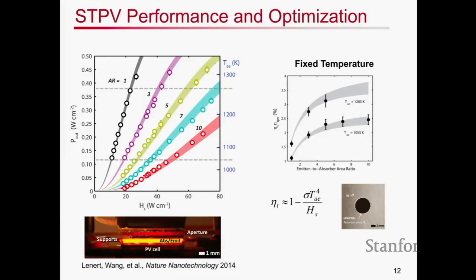Okay. So you can see here, as you increase the area ratio for a fixed temperature, you're essentially improving the thermal efficiency of the process. And the reason for that is you're increasing your irradiance such that it outpowers the emissive losses. So your thermal efficiency in this case will continue to increase as a function of the area ratio, but you're increasing your irradiance to maintain the temperature that's ideal for the emission to the PV cell.